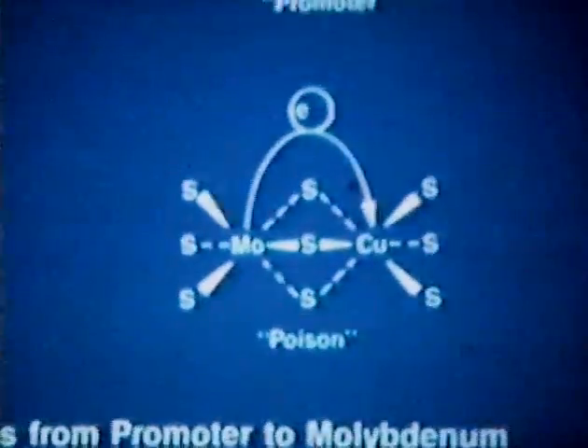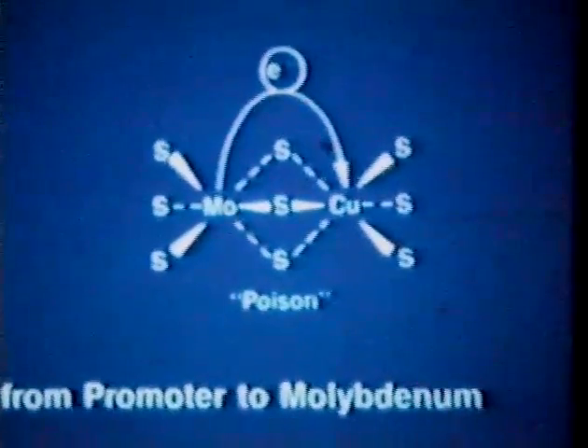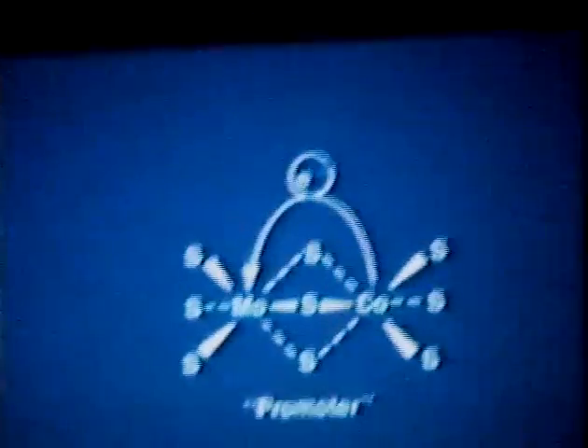So we would generate a modified activity parameter. Basically, the other factor I talked about, covalency, roughly stays the same, so it's just this counting. Here again is a comparison of the activity parameter shown on this slide against some measurements made in DBT, again showing rough quantitative trend results using this picture of electron transfer at these special sites on the edge.